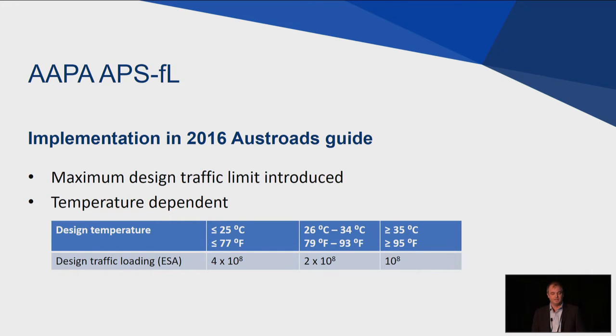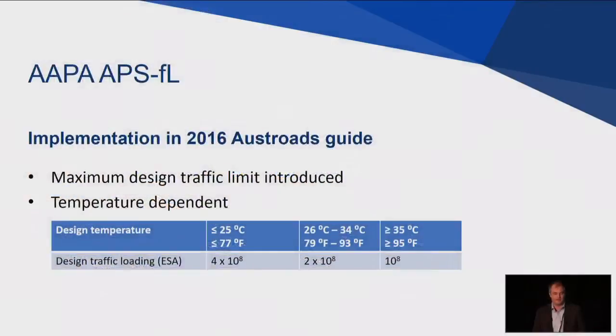Those limits are temperature dependent, and that is to recognize the influence of modulus on that fatigue endurance limit. It is also a recognition of the fact that the states in the south of the country, where it's a little bit cooler, were more comfortable with the thicknesses they were getting out of their design method than the states further north, where it's warmer. I've put the design temperatures there in Celsius and Fahrenheit. Basically, for Queensland, you would be designing pavements for no more than 200 million equivalent standard axles, which seems like a lot, but if you consider that pavements in Australia are typically designed for 40 year design periods, that's not unheard of.